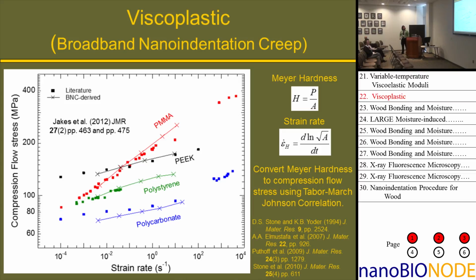And then finally, one other thing, the thing that I did back for my PhD, I'm also looking at viscoplastic properties. And there's some debate about what a hardness measurement means in a structural polymer like these. So what I did was I carefully measured Meyer hardness as a function of indentation strain rate by loading up the indenter and then watching how the area grows at a constant load. And then you can calculate Meyer's hardness as a function of indentation strain rate. And then using this 50-year-old Tabor-Marsh-Johnson correlation, you can convert the hardness to a compression flow stress like you'd measure in a uniaxial test. And if you go through this analysis, you can almost exactly reproduce what you get in the conventional uniaxial test. And this work was built off of a lot of previous work done in Professor Stone's group to develop a creep analysis.